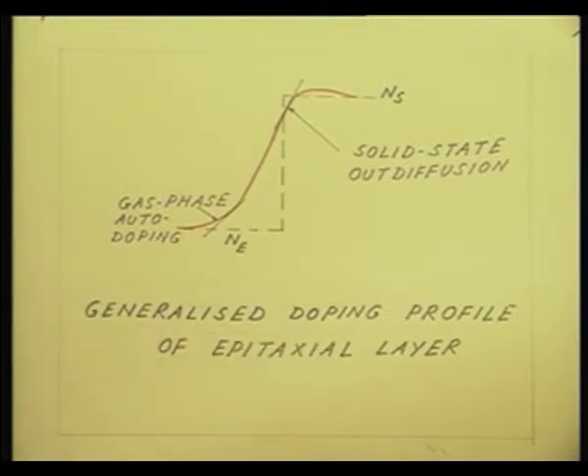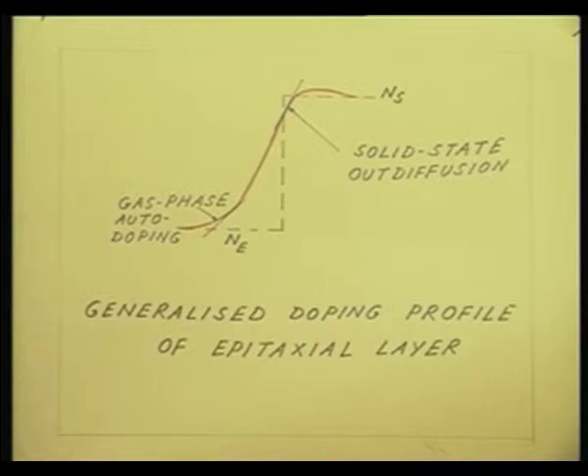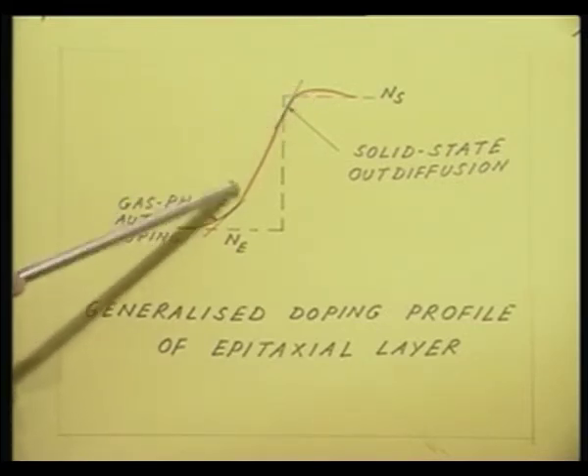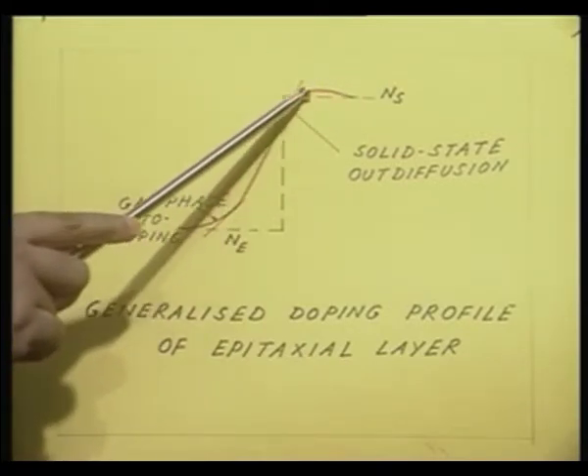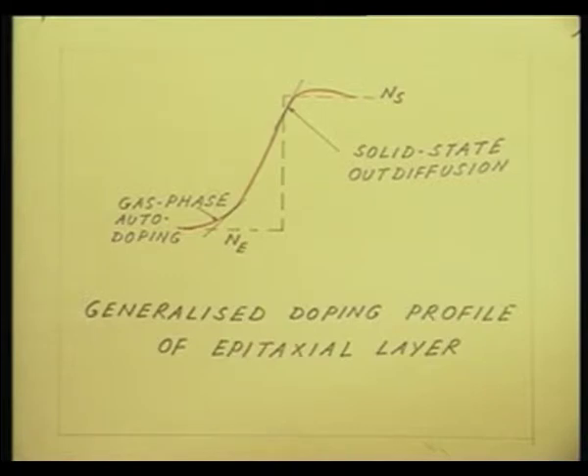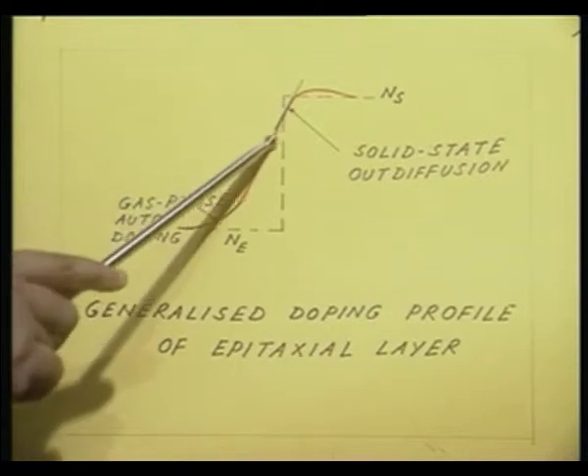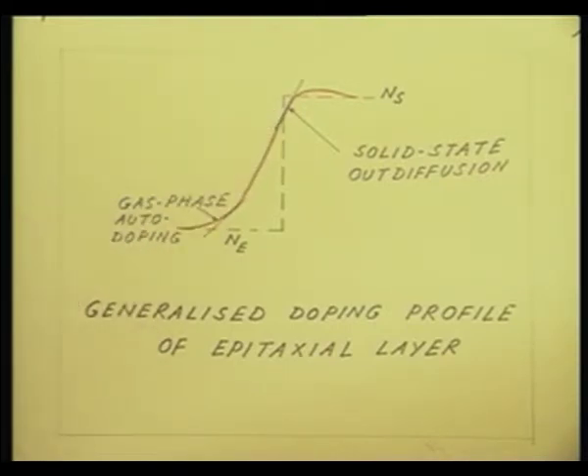I call it a generalized doping profile. That is, here both the effects of auto doping can be seen: the solid state diffusion as well as the gas phase auto doping. It is very easy to understand that the solid state out diffusion will be predominant at the interface region. This is the high concentration side, this is the low concentration side. Therefore, the dopants will try to diffuse from the bulk region into the epitaxial region, and therefore, the doping concentration in the epitaxial region here will be quite high. It will not abruptly fall down to the level you desire. So, this portion is dominated by the solid state out diffusion and can be modeled by an exponential relationship.